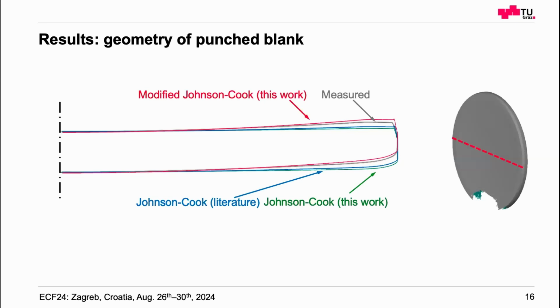At the end, I want to give a short look at the parts we measured. You see, we made a cross-section through the scan and compared this with our simulations. Gray is the measured real part. And you see there is a difference to the Johnson-Cook standard model, which we determined, and also with the Johnson-Cook parameters from literature, there's a difference. And our modified Johnson-Cook model is quite the same as the real measured part.